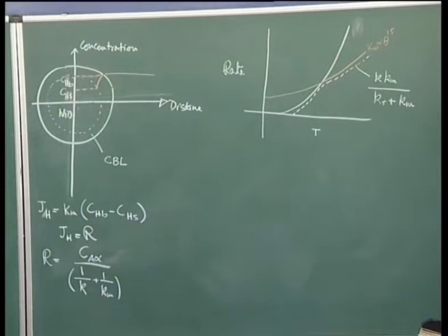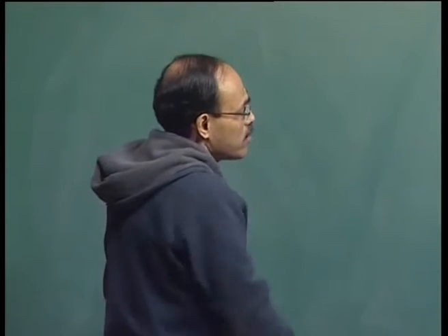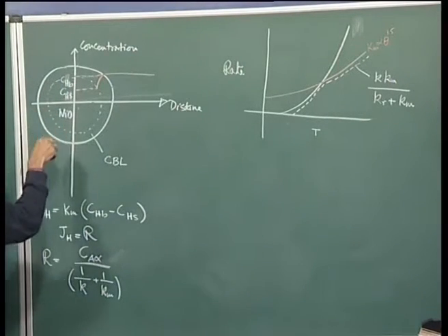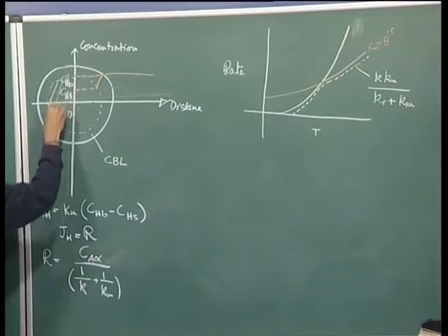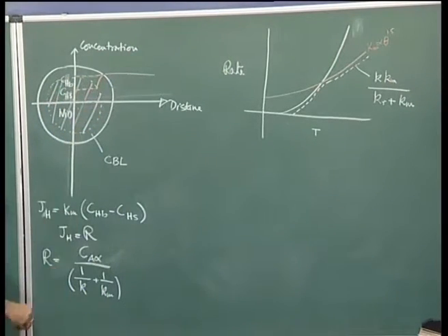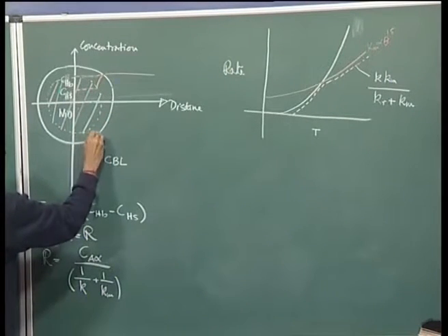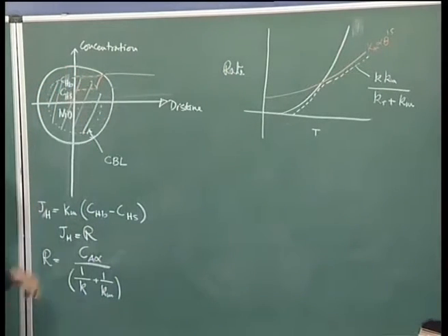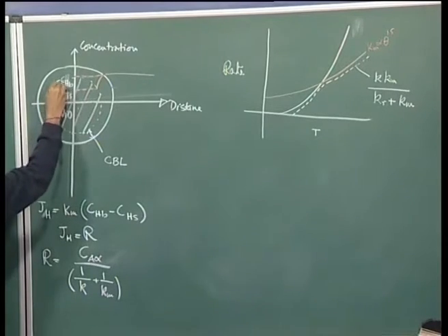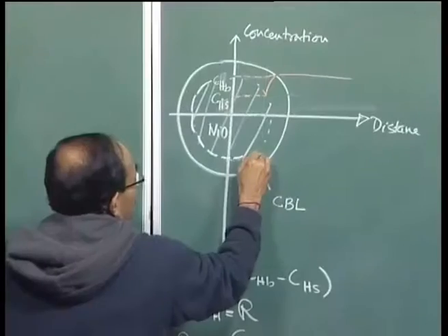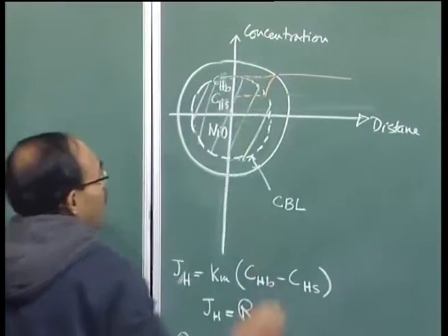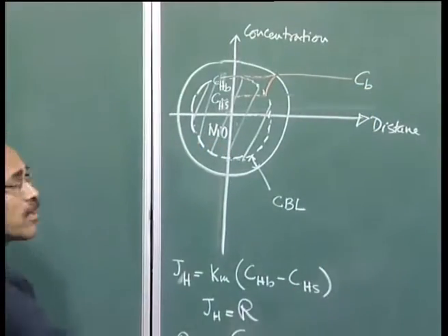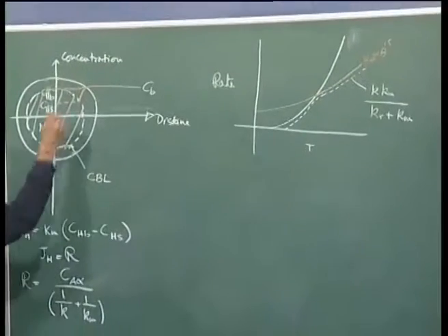Just now I have written on the left the nickel oxide hydrogen reaction. So this is what I have intended to draw here. This is the nickel oxide sphere actually, and whatever is shown here, this distance is the concentration boundary layer. The outer solid line represents the boundary layer and the solid nickel oxide is this. Now, this is the bulk concentration, and as per our assumption the bulk concentration prevails right up to the interface, and then it drops